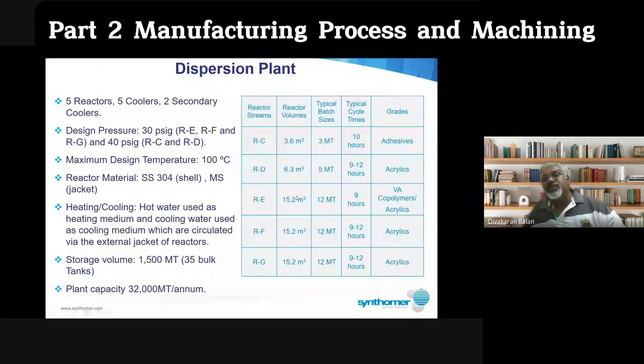Then reactor D is 6.3 cubic meters, and each batch is about 5 metric tons. The cycle time is 9 to 12 hours. And the grade of product we produce is acrylics. By chemistry, we have 3 different types of products: one is acrylics, one is vinyl acetate, one is adhesive. If you see VA copolymer, it means you use multiple monomers in this product. Normally acrylics is a mixture of styrene monomer and butyl acrylate. VA is vinyl acetate, VAM, vinyl acetate monomer.